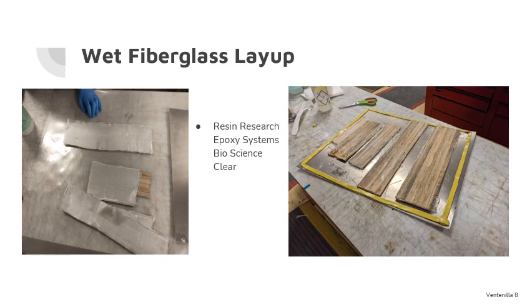After that, we were able to cut up the board into the sizes we needed for our test samples, and then we put a layer of fiberglass over the top of them and then added resin to the top of the fiberglass in order to get the test samples we needed. And now I'll pass it on to Scout for the material tests.